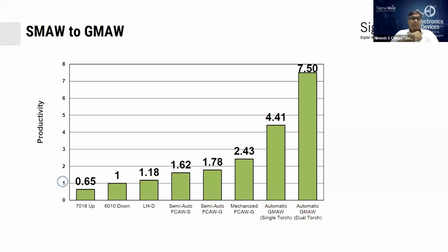If you mechanize it, that means put this onto a trolley, we will see all that later, you can get a deposit of about 2.43 kgs. And if you completely automate GMAW, that is gas metal arc welding, deposits can be as high as 4.41. And with dual torch or dual wire, we can reach up to 7.5 kgs per hour. So moving right from 0.65 to 7.5 is possible.